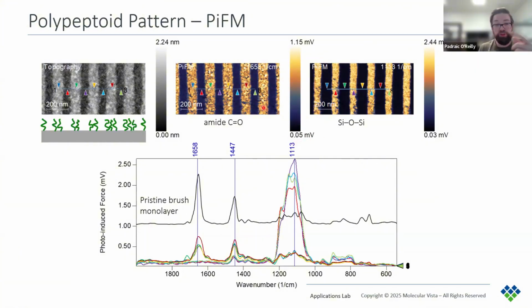You can see from the topography here that these peptoid lines are only about 1.5 nanometers tall, but they're easily identified with PiFM. So this shows the benefit of PiFM over relying solely on water contact angle and ellipsometry measurements.